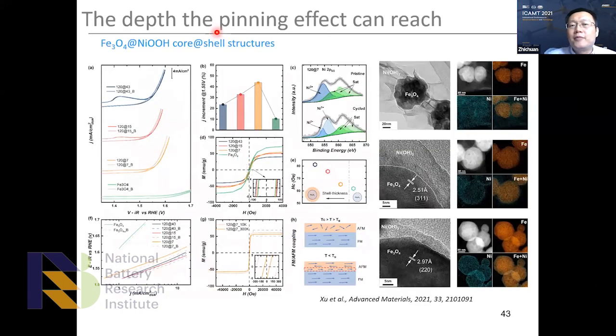Okay, now let's look at the shell effect. Let's see how far the pinning effect can reach into the top layer, right? So we change the thickness of the surface layer from 7 nanometers to 15 nanometers and to 43 nanometers, and we can observe that thinner is actually better. If it is thinner, for example 7 nanometers, the phenomenon is significant, or let's say remarkable. But if the top layer is much thicker, we are not able to see that. This is consistent with the principle of the pinning effect. They only happen at the interface, and that is in the range of a few nanometers.